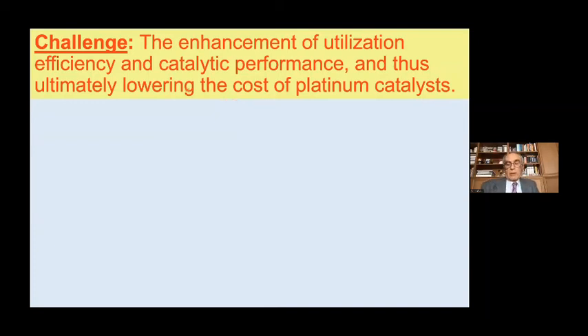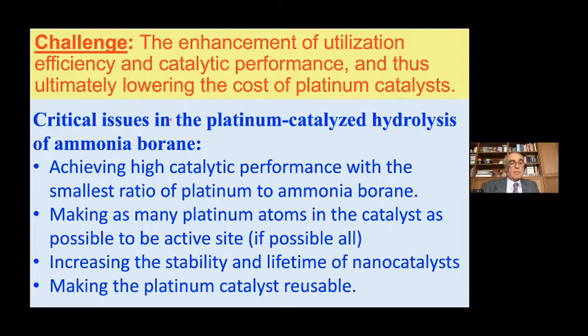So I will show that there are issues in this concern. The first one is achieving high catalytic performance with the smallest ratio of platinum to ammonia borane. As you know, the catalyst to substrate ratio in catalysis is very important parameter. It should be as low as possible. So for the platinum in ammonia borane, that ratio should be as small as possible. That's one way. Or making as many platinum atoms in the catalyst as possible to be active site.